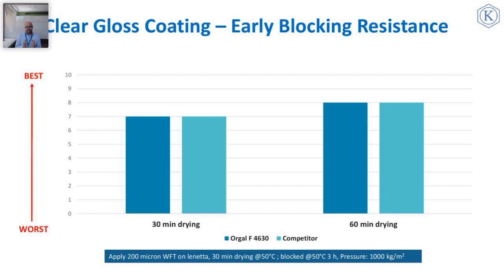In a 0 to 10 scale of assessment, and 10 being the best performance, both binders were found 7 after 30 minutes of drying and 8 after 60 minutes of drying. 7 and 8 means panels were able to be separated with a gentle force and surfaces were not damaged. For an industrial wood coating application, good blocking resistance results were achieved.